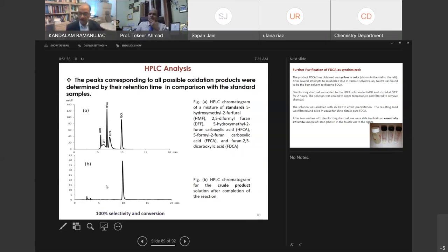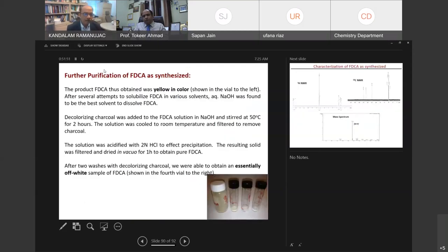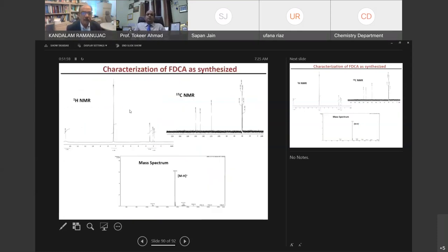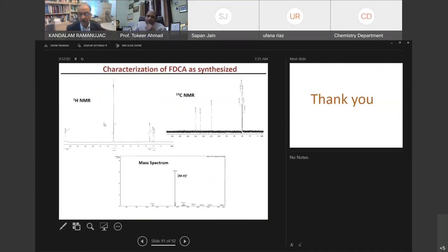As you can see, the Li2CoMn3O8 selectively oxidizes HMF to FDCA without any presence of partial oxidation products. This is a very, very important thing. And then, of course, once you make this compound, you further purify. For organic chemists, that's very normal. So, you go through recrystallization, decolorization. And finally, we did the proton and the carbon-13 NMRs, and we find the exact match to that of the FDCA. So we successfully, catalytically, efficiently, and selectively converted HMF using a different design of the transition metal oxide spinels.